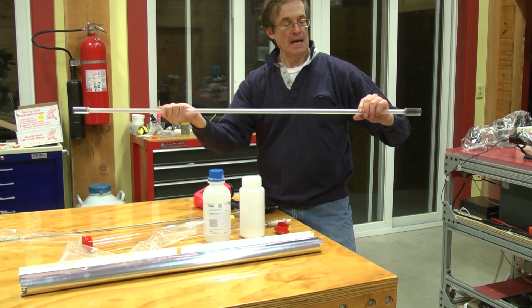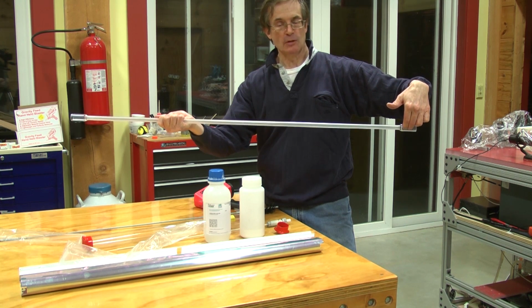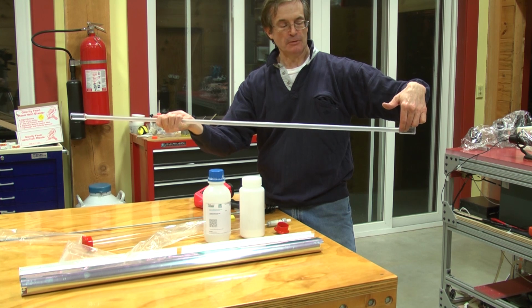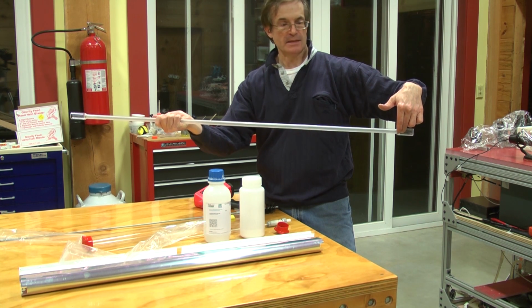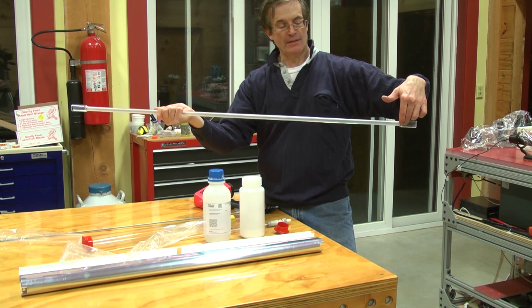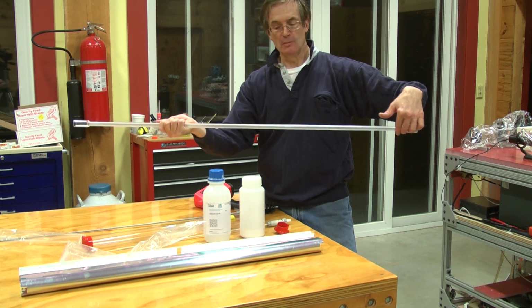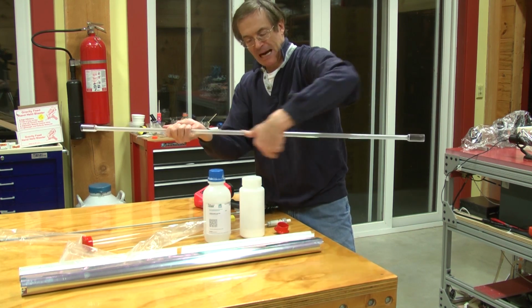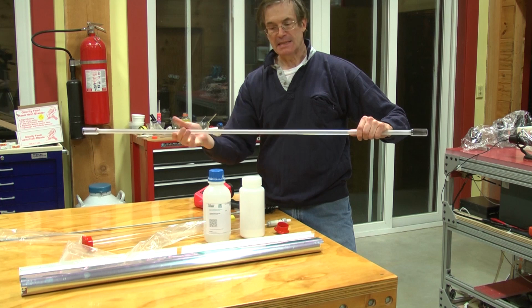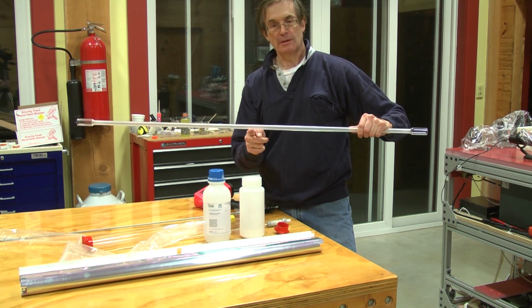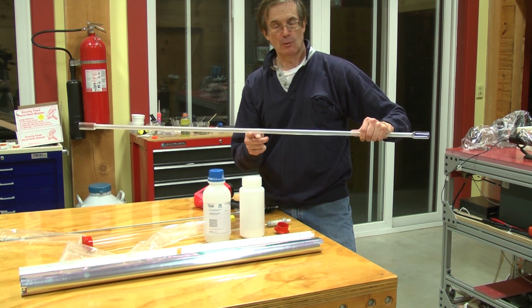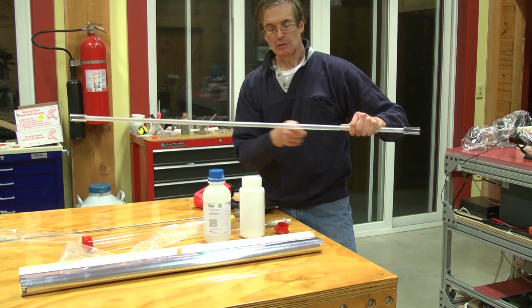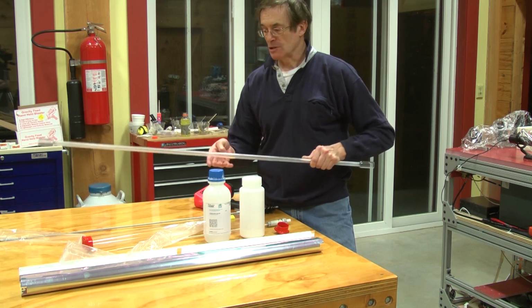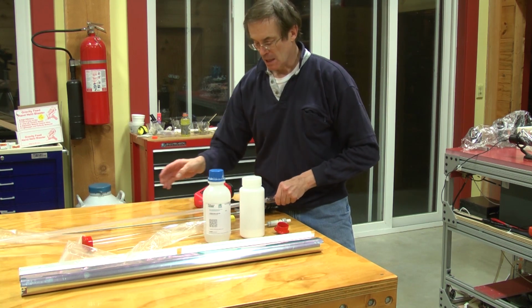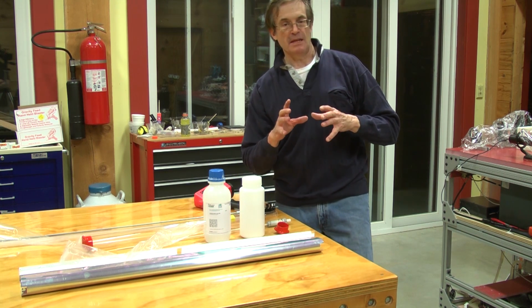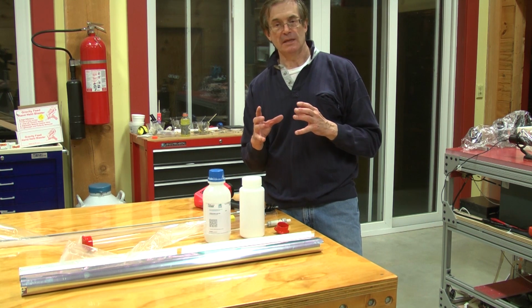downward direction. I then mark the sides of the tube, and if you go back to the video earlier on, you'll see that there's a couple of black lines on the side of my dye cell that's actually installed in the laser. And therefore I know that when I mount the tube, its bow is in the perfectly downward direction. It's then easy to place a small support underneath here to elevate it maybe 0.5 millimeter or whatever is necessary to make it absolutely straight along its length. So by using these techniques, I've gotten a very convenient method of getting very high efficiency out of the laser.